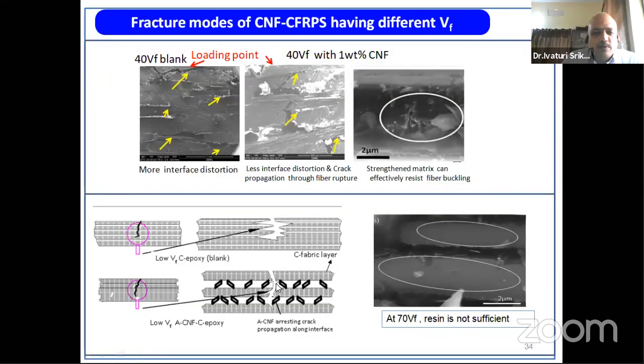When you make a low VF composite, these are the reinforcement layers. These are the nanotubes. The matrix thickness in the interfacial zones is very high. So crack propagation through these interfacial zones between two layers, in the case of a non-CNT composite, will be easy. So it breaks easily. If you add CNTs, these CNTs will resist the crack propagation. These are some of the crack propagation images shown here. So that results in significant improvement in the flexural strength and even shear strength.